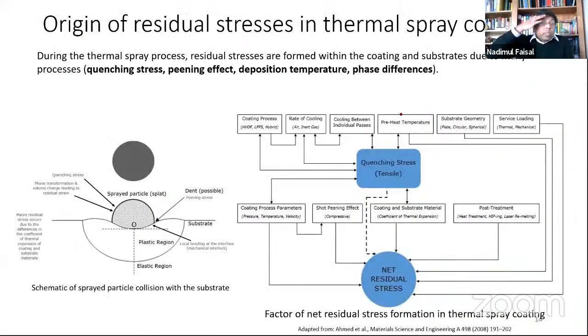Right, so in thermal spray, there are some factors because of which residual stress builds up. Those four, I would say, are the quenching stress, the peening effect, the deposition temperature, and the phase difference. So a combination of these will have an impact on the residual stress buildup.